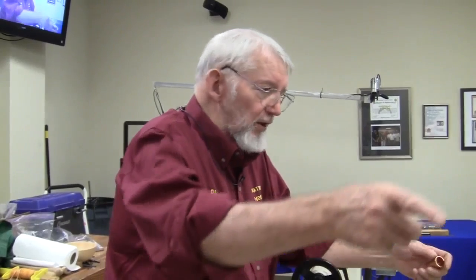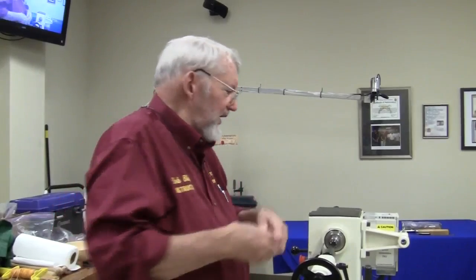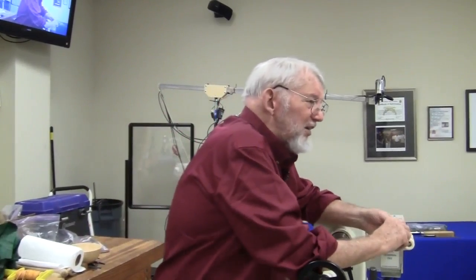I think the silver solder starts at about 20% silver. Harris Welding is one of the places that handles all that. An ounce of it 3, 4, 5 years ago cost me like $22. A can of flux is $5, and it's freight. I was using 1/16 diameter wire, and that's too thick for the small tool that's coming around. The highest content of silver is 55%. Obviously the most expensive, but we're talking the difference in $15 to $22 or something for an ounce. It comes in a little metal can, nice little coil. It melts, I think, in the 950 range.